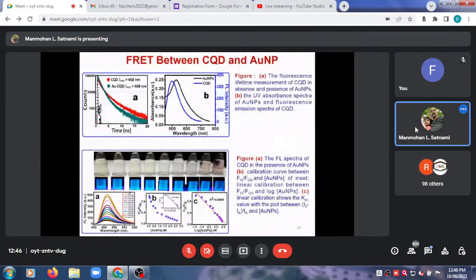Yes, the most important thing for the FRET process to happen is that there should be an overlap between the fluorescence spectra of carbon quantum dot and absorption spectra of gold nanoparticle. So you can see from figure B, the blue line is the emission spectra of carbon quantum dot, and the black line is absorption spectra of gold nanoparticle, and both are overlapping. So this is very important.